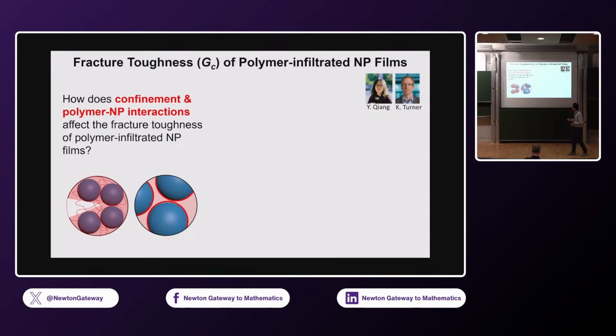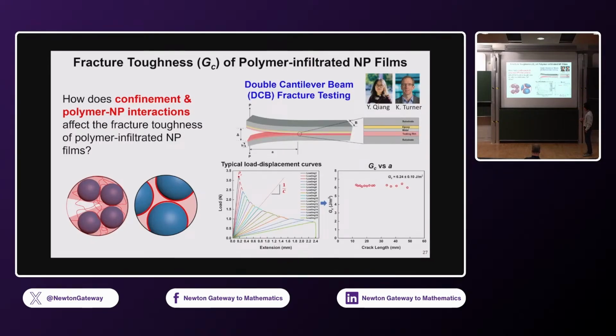Okay, so Kevin Turner, my colleague in mechanical engineering, and I had a very talented student who was able to perform this double cantilever beam test. It's a test that's been really exploited by Dauskardt at Stanford, where we want to propagate a crack over a long distance in order to get a reliable measurement. So we make this sandwich sample where our composite film is sandwiched between two very, very stiff beams. These are silicon wafers, basically, okay? And then we induce fracture and let the crack propagate through our film, and we measure the response, okay?